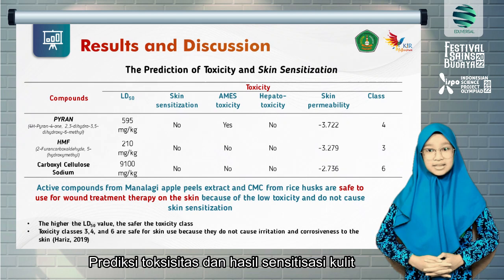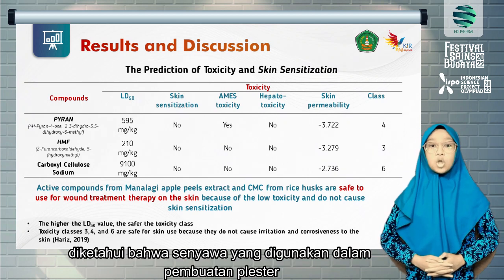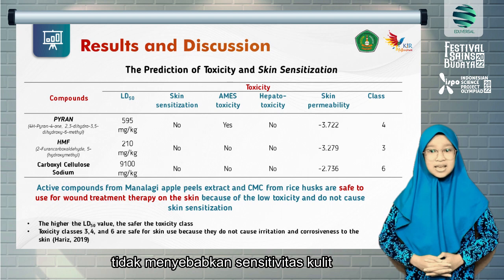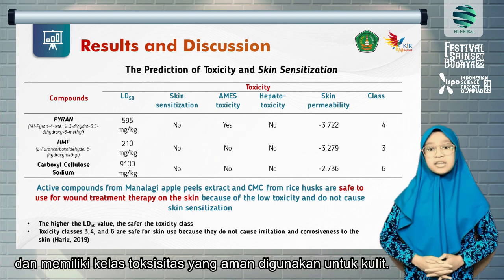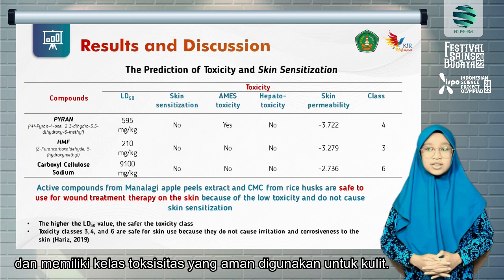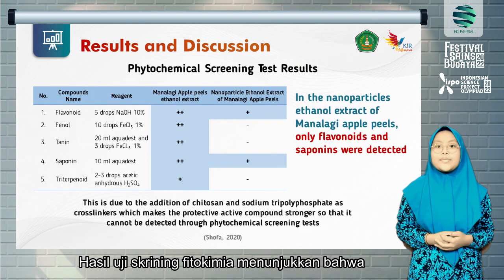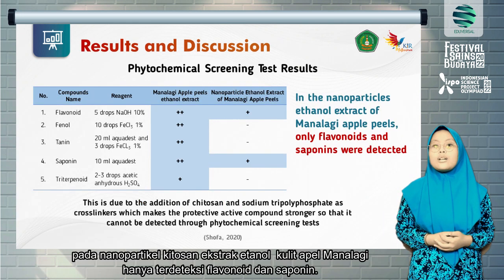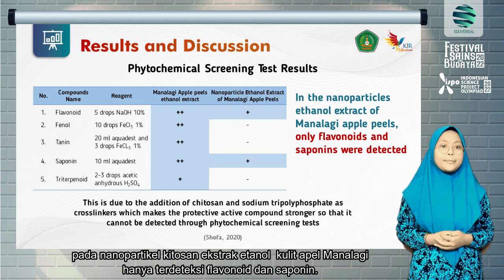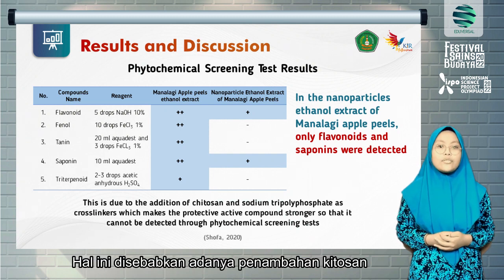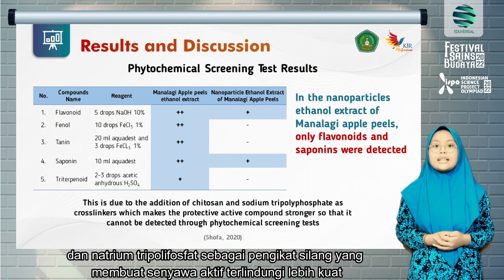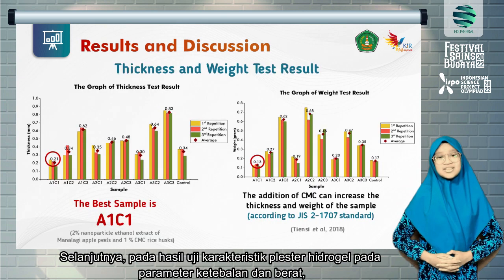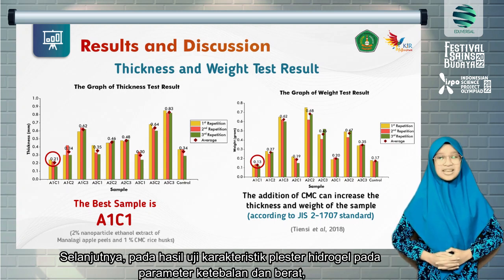From the prediction of toxicity and skin sensitization, it is known that the compounds used in the making of patches didn't cause skin sensitivity and have a toxicity class which is safe to use for the skin. The phytochemical screening test result shows that in the nanoparticles of chitosan ethanol extract of manalagi apple peels, only flavonoids and saponins were detected. This is due to the addition of chitosan and sodium tripolyphosphate as crosslinkers, which makes the protective active compound stronger.